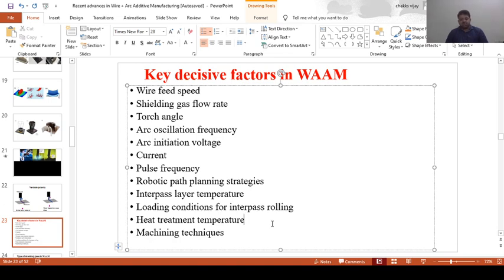If we are going to make a heat treatment, then we should be aware of the specific temperature and the specific duration we are supposed to do heat treatment. For example, stainless steel 316L, we generally go for 660 degrees Celsius for 6 hours. In case of aluminium, it would be rather different. So heat treatment temperature should be one of the most concerned factors.